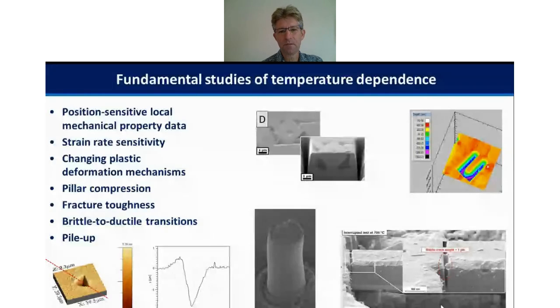and show how those build up to give you the bulk scale performance that you get. You can also look at time-dependent deformation and things like strain rate sensitivity and creep behavior, and how this is affected by the changing plastic deformation mechanisms in your materials, and that may also affect the amount of pile-up that occurs around the indentation. And you can also look at the ductility of small-scale structures and materials, particularly those that are brittle at room temperature. So you can look at machined pillars and machined micro cantilevers, and I'll talk a little bit about that later on.